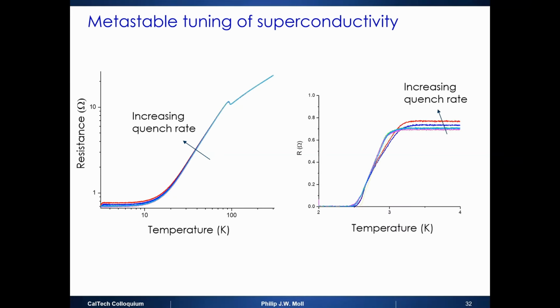What is quite remarkable is the response in the superconducting state. Very clearly, with increasing quench rate, the onset of superconductivity goes up. And this is reversible. You can now do a slow current pulse, and then TC just goes back to where it was before. You quench it again, you go up and down, up and down.